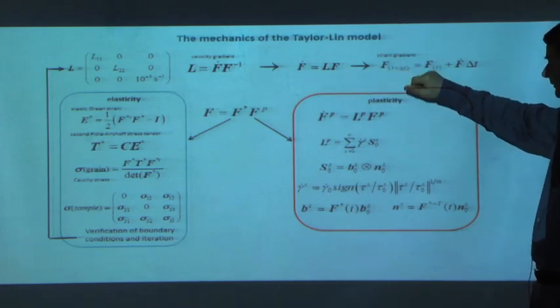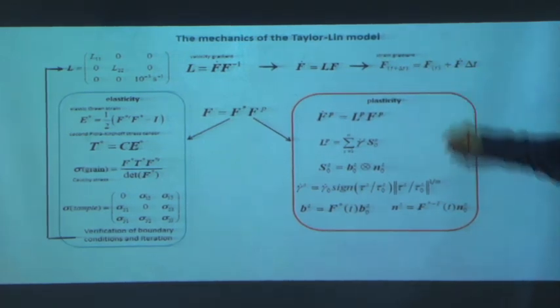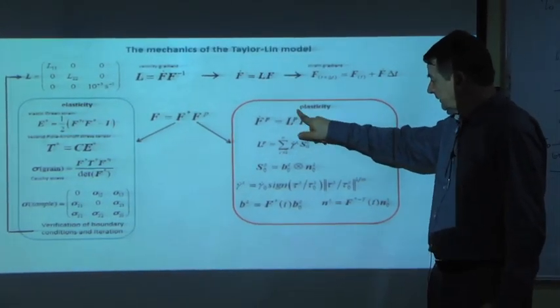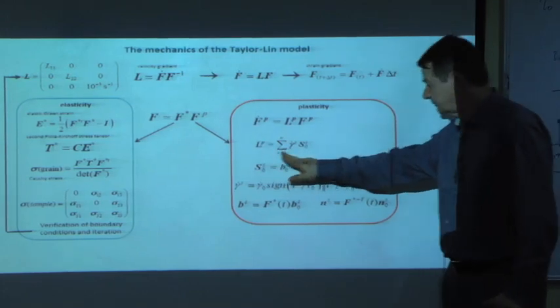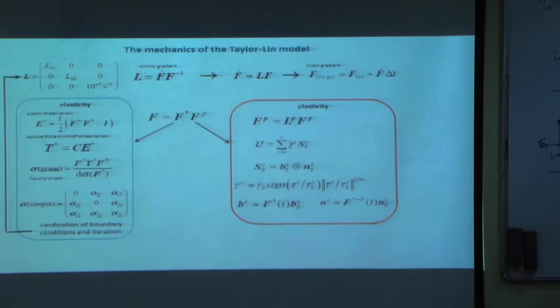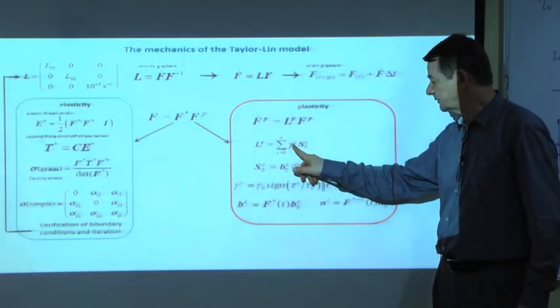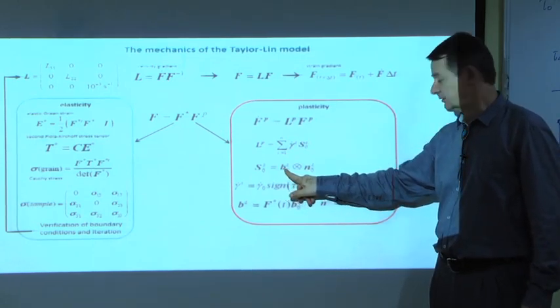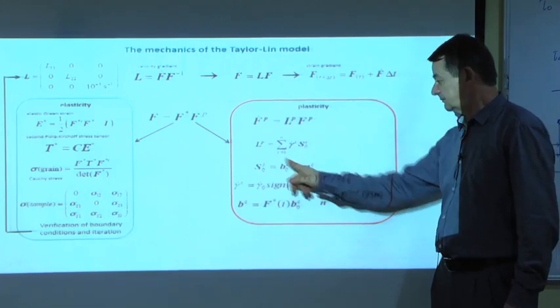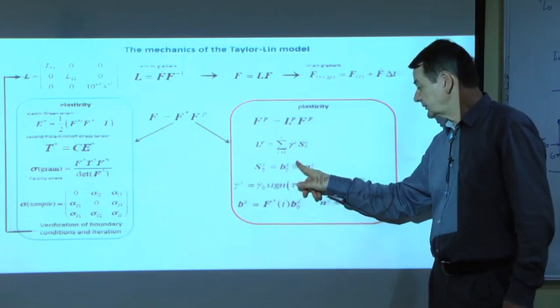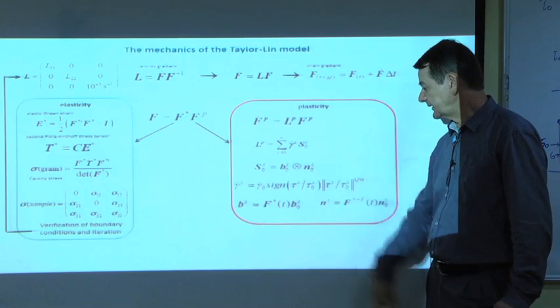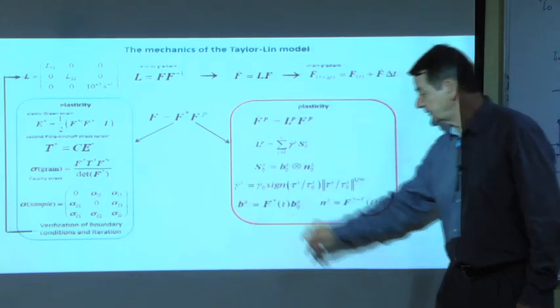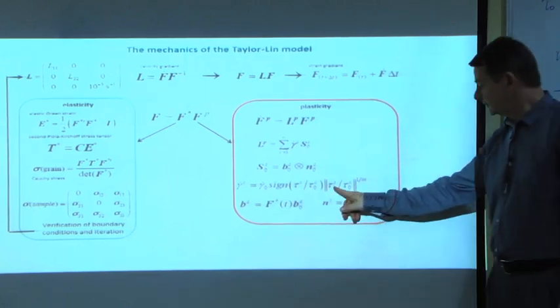In that approach, one has to know the strain gradient, which is decomposed into Lp and Fp. This is the plastic part of the strain - the plastic velocity gradient Lp - which is made by slip: gamma-dot times S0. S0 is the Schmid tensor, which is the multiplication of the slip direction and the slip plane normal. For the slip rate, we use the viscoplastic slip constitutive law with tau-zero.